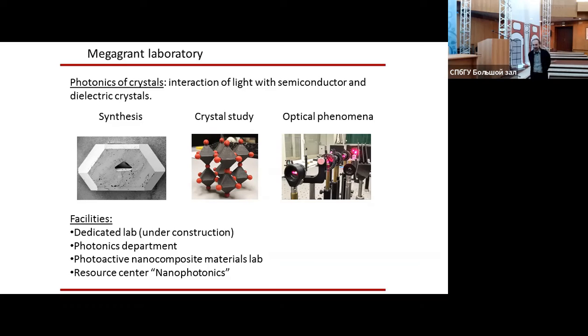Yeah, I have an answer for this, and that's a very good question. Normally, when you think about semiconductors, you think doping. Perovskites cannot be doped, because they are ternary systems. Let's say you try to dope the B side, the metal side, then you will lose some of the A side to compensate. But it will not dope electrically. It will lose the cation, so it will lose the ion and it's happy, no doping. Same goes for the halogen. If you try to change the halogen, again, it will compensate for the other side. So you cannot dope it intentionally.